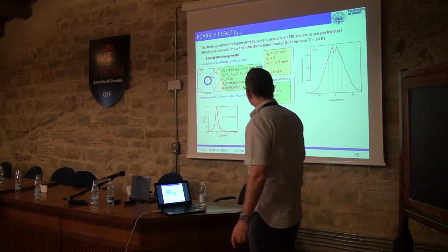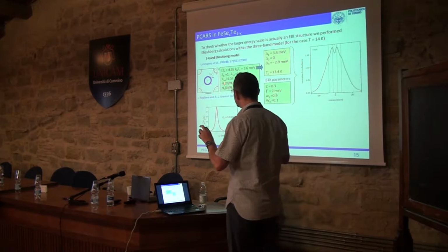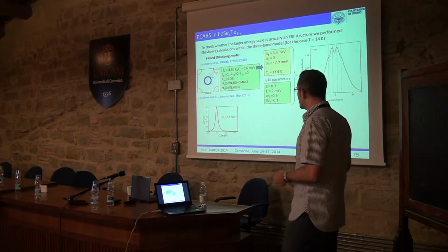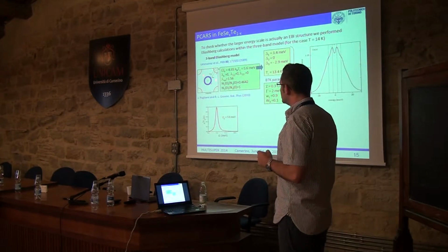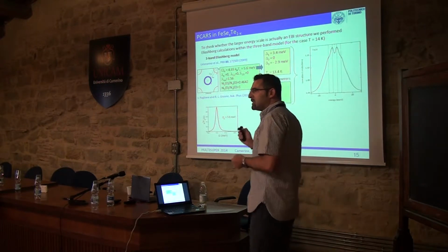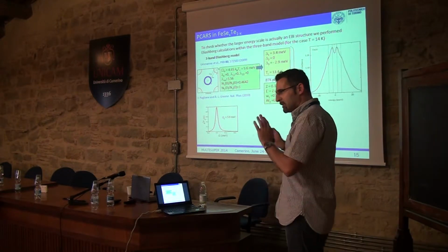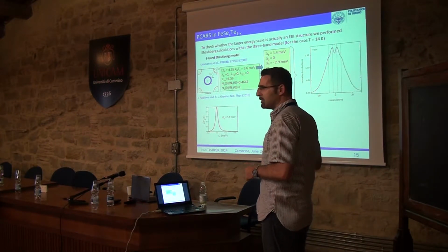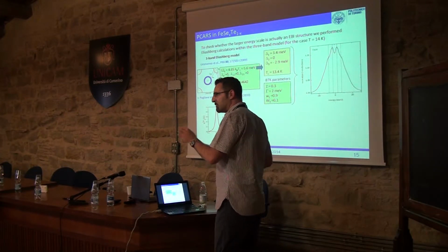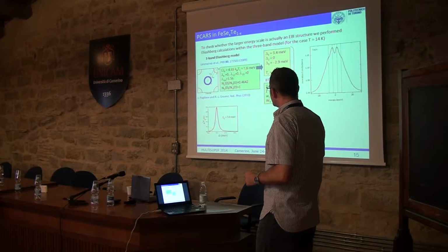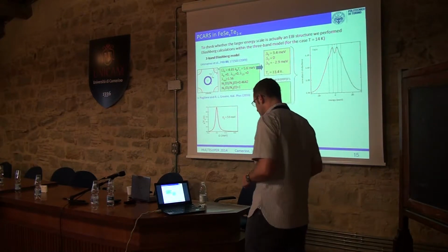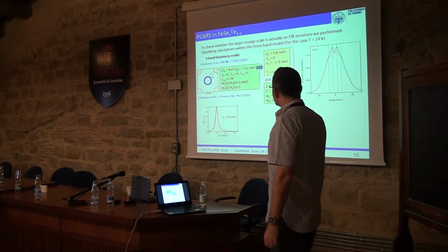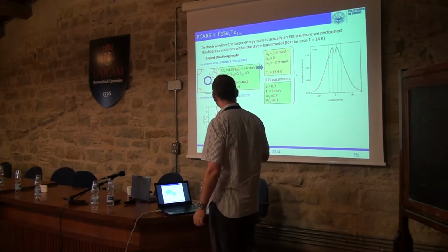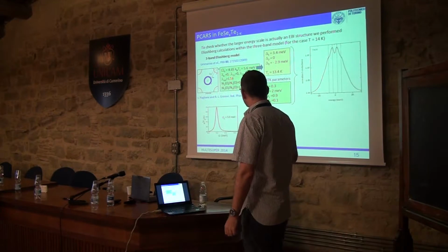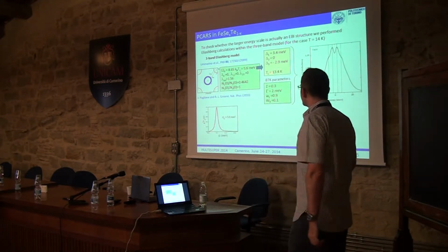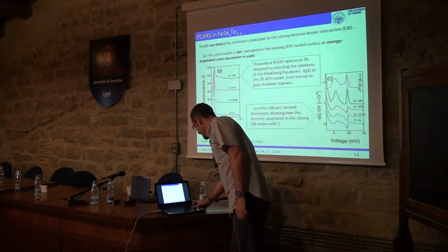So we use an effective three-band. It is maybe not the three-band of the sample, but the effective three-band is the minimal model that can reproduce our results. So we use this minimal model, supposing that the coupling is due to spin fluctuations. I'm not saying that I'm sure that they are, but suppose that they are spin fluctuations. So the Lorentzian shape mimics the shape of the spin fluctuation spectrum. The peak is put at the energy that corresponds to a law which has been found experimentally that relates the Tc to the energy of the spin resonance. Then we need the ratio of the density of states, but this is a detail. We obtain the gaps in such a way that they lie here.